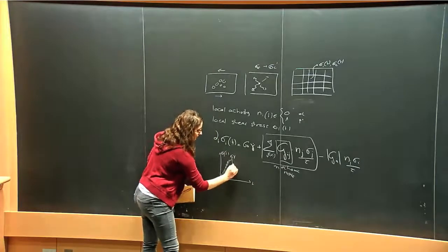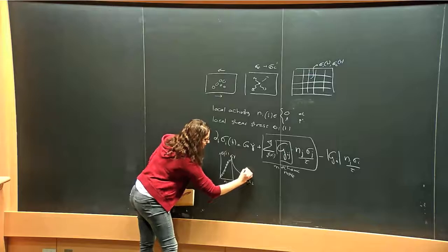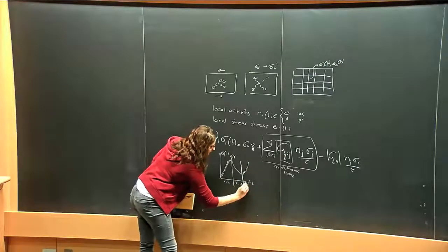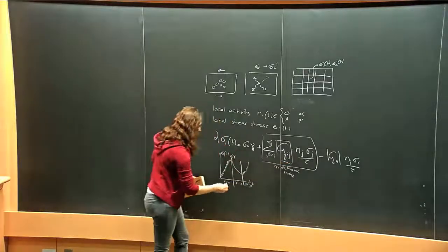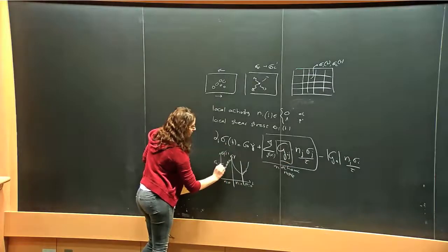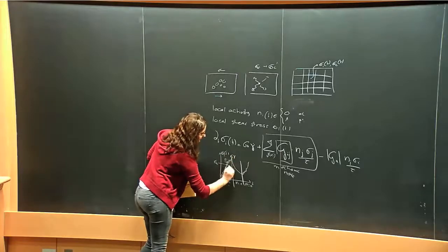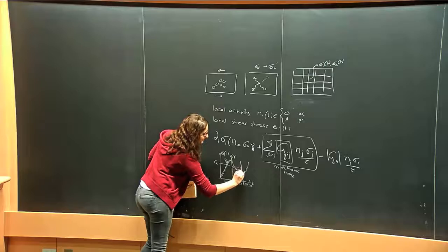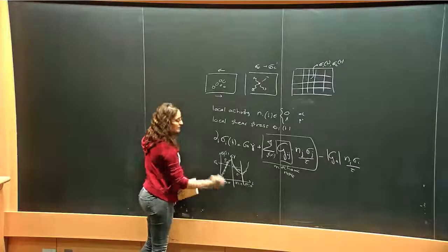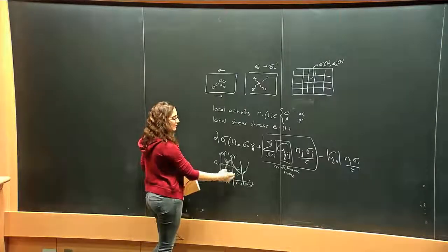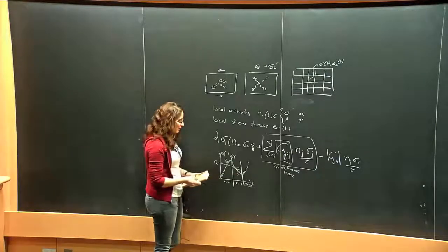Then at some point, you will have a rearrangement. So this is n equal to 0, n equal to 1. And at some point, you will become elastic again, n equal 0. So one choice you can make for the stochastic rules for this n could be to say, you have here a local yield stress. Once I'm above, I have a typical time before I start yielding. Then I will have a typical time during which I will be plastic. And you can also include the typical time scale on which you relax. So you could study the dynamics just having those three typical times. And how this would be related to experiments, that would be a question.